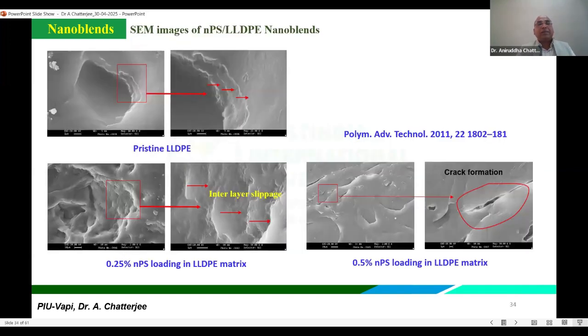So here you can see what happened after the addition of nanoparticles. There is interlayer slippage, you can see over here. The polymeric nanoparticles are acting as a lubricant, as well as providing strength in that particular matrix by holding the large molecular chains of the polymeric matrix. That's why tensile strength as well as elongation at break are both increased.